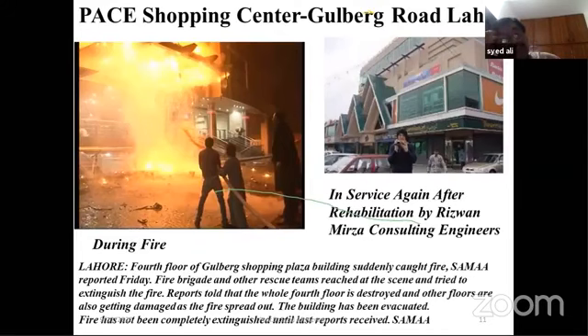So later on, we took some core samples from slab elements. And first of all, I tell you for your experience, we examined the color of concrete at various locations. At various locations, the color of concrete differed. At some locations, the color of concrete was simply kind of black, which indicated that a huge fire load had struck it. At some locations, it was pink. If you see a pink color, then you can assume that the hydroxyl group of concrete has left the concrete, and the remaining are the voids. Hydroxyl group means calcium hydroxide, potassium hydroxide, sodium hydroxide, and something like that. Because calcium hydroxide is the main product of hydration of concrete.